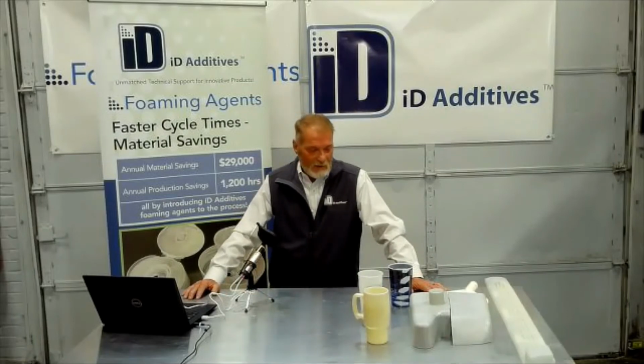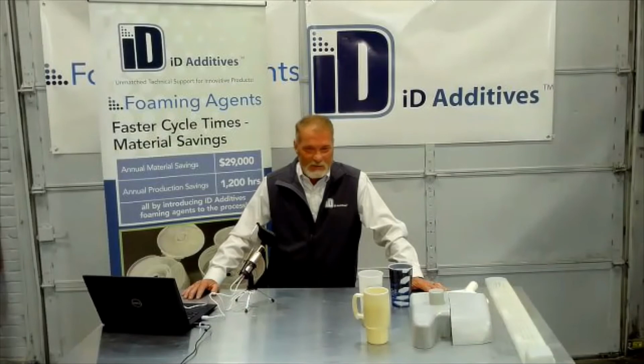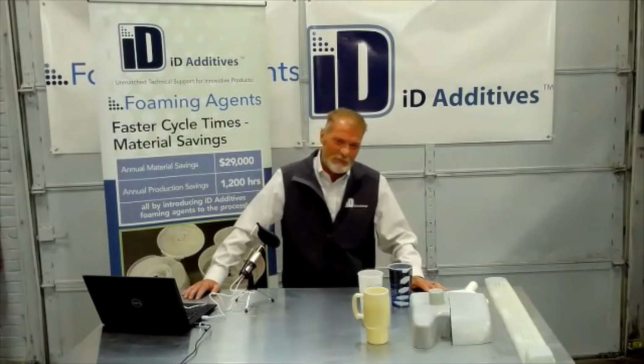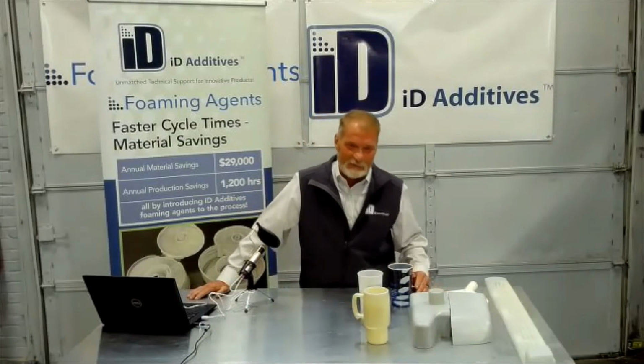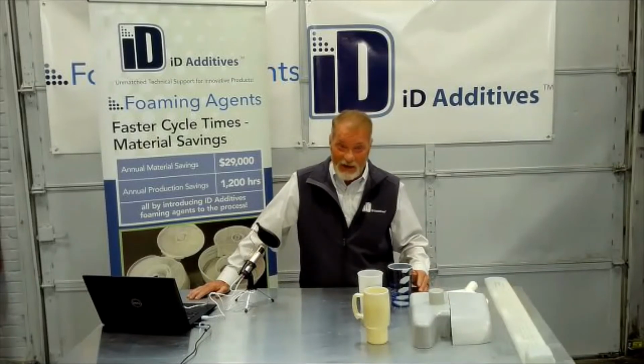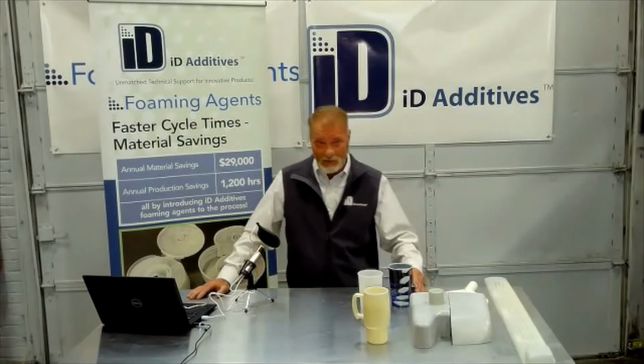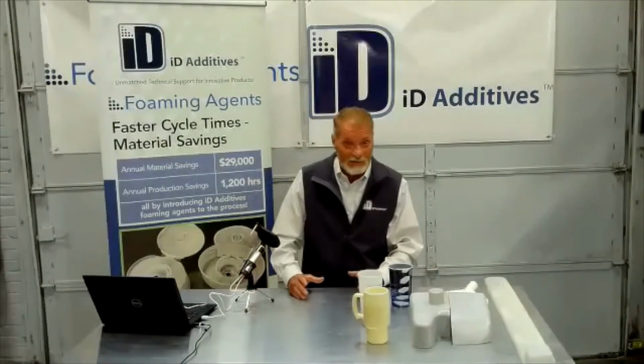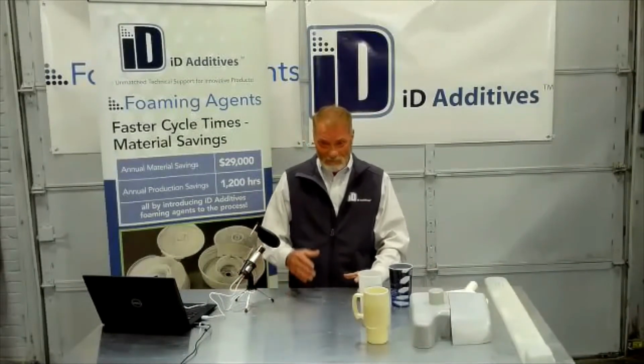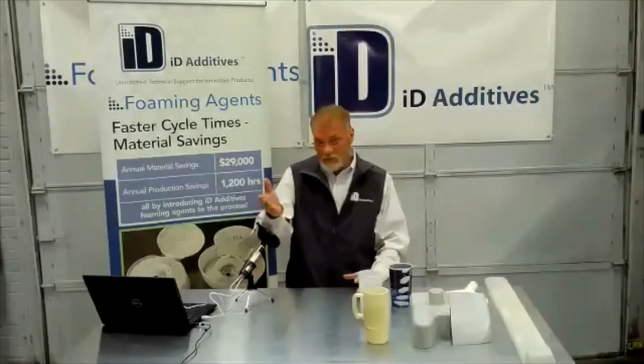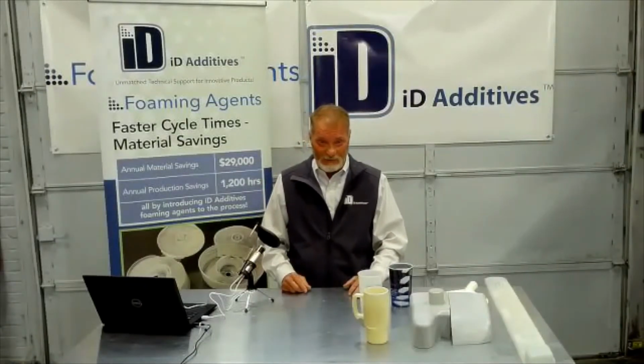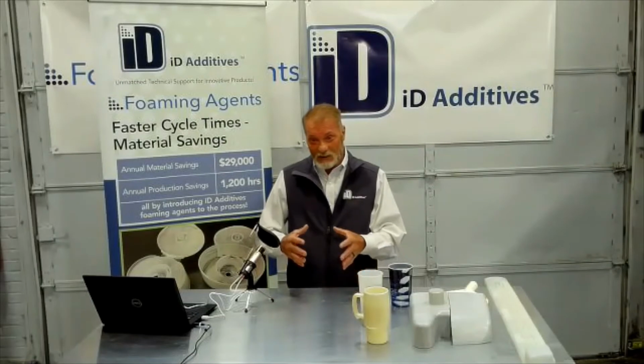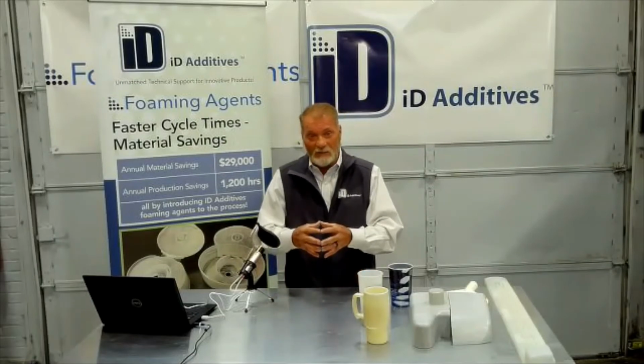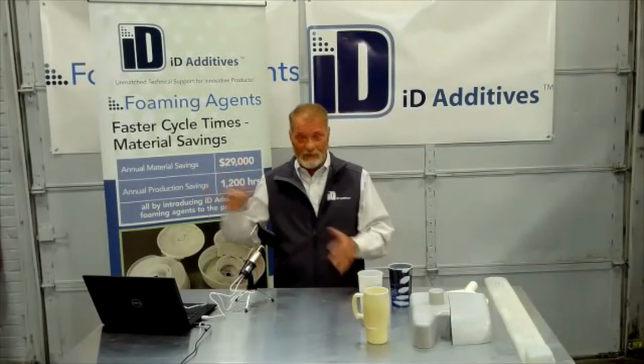When people say, well, I've got 30% glass, 30% talc, what have you, and we take 4% weight out. Well, 4% is not a lot, but when you look at the polymer by itself, it's actually higher than that. The whole weight is 4% lighter. But remember, with the foam, only 50% of that is what you're foaming. So if you're looking at what you're saving in the polymer itself, it's more than 4%, if that makes sense.